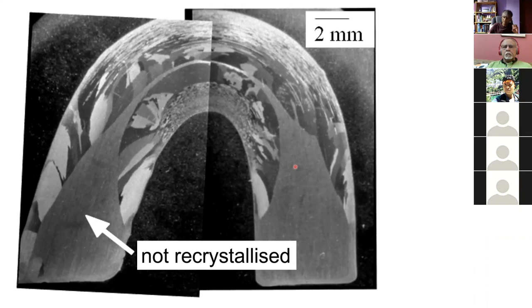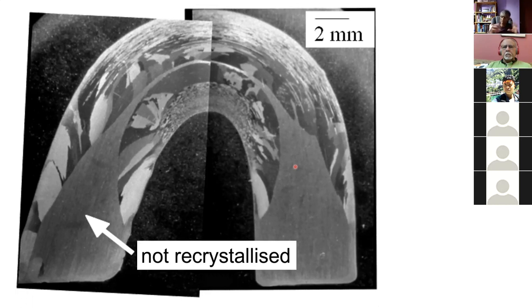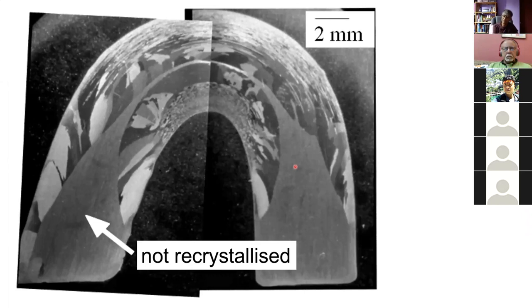Currently there are many projects on this material because of the fusion reactor. If you have oxide particles dispersed inside the material, they act as nuclei for helium bubbles. In a fusion reactor, the neutron flux is much greater than in a fission reactor, so helium produced by transmutation inside the steel would cause swelling if there aren't enough nucleation sites. Just as it's harder to blow up a balloon at the beginning, a pore holds more gas when small. With many nucleation sites for bubbles, you hold far more gas in very small cavities and the material doesn't swell during irradiation.